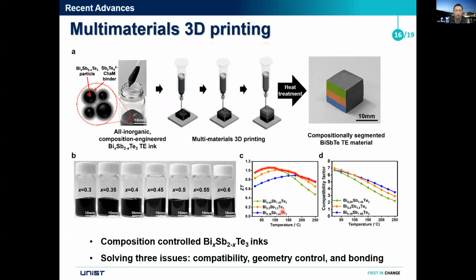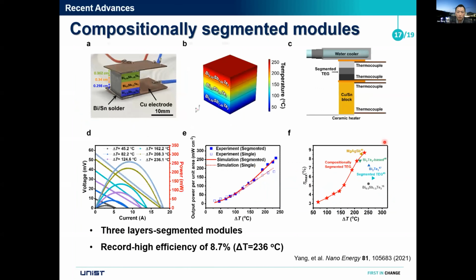So for the segmentation of thermoelectric material, we have realized a multi-material sequential 3D printing technology. By using this process, we sequentially deposit 3 different inks and then get this multi-junction bulk material. And by adjusting the property of each layer, we realize very high average ZT values in this material. And then we have measured their power performance.